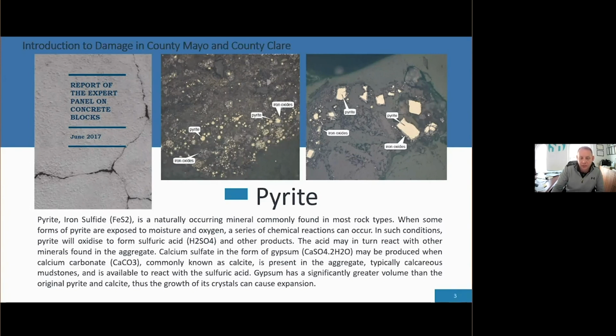And calcium carbonate, commonly known as calcite, is present in the aggregate, typically calcareous mudstones, which is the main aggregate source that we've noted in Mayo and in Clare, and is available to react with the sulfuric acid. Gypsum has a significantly greater volume than the original pyrite and calcite, thus growth of its crystals can cause expansion.